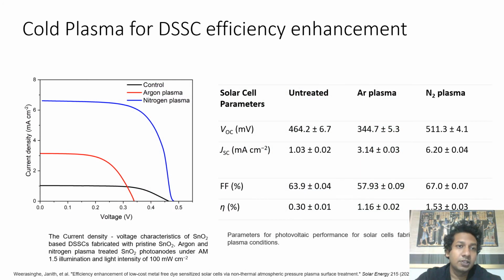Tin oxide photoanodes exposed to the argon plasma show an increase of photoconversion efficiency over the controlled DSSCs. This enhancement can be attributed to the removal of the surface impurities due to argon plasma treatment. DSSCs fabricated with the photoanodes exposed to the nitrogen plasma showed the highest efficiency due to the combined effect of removal of surface impurities and the decrease of oxygen vacancies. The nitrogen plasma functionalized surface of the photoanode provides more anchorage to the sensitizing dye molecules compared to the pristine tin oxide, yielding a significant increase in the photocurrent.